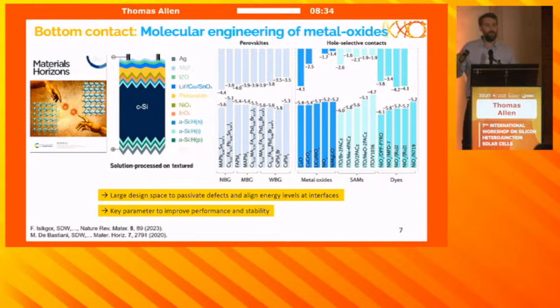Okay, so I'll now move to the HTL contact. With a lot of really great work done at HZB and with Kaunas, developing these phosphonic acid-based self-assembled monolayers, we have very nice HTL contacts now. And with some chemical modification to those SAMs that are deposited and anchored to the TCO of the underlying silicon cell, you're able to get very nice tunability in the valence band position. And this is great, not only for passivating defects, but also aligning the energy levels at the contact interfaces. And this is good not only for efficiency, but also stability, which I'll show here.